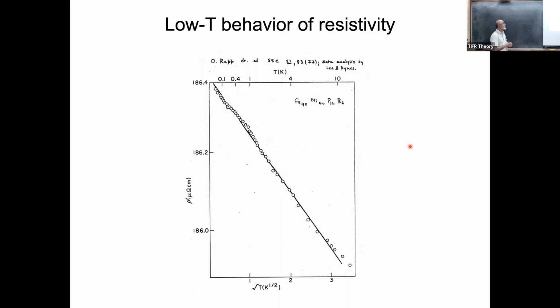At that time, they were finding that resistance basically goes up at low temperatures in a metallic system. And they were trying to understand that in terms of magnetic scattering and Kondo impurities and things like that. And so they were trying to figure that it looked like log. However, when Patrick Lee and Bob Dynes analyzed the data and plotted it versus square root of temperature, you see the data lie on a perfect straight line, suggesting that, in fact, this is just a dirty metal.